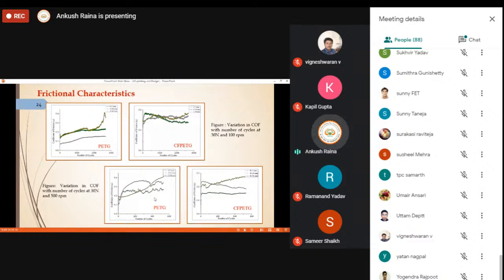So a similar case study has been done at the high speeds. Here you can see again there is an increase, and the coefficient of friction is in the range of 0.2 and 0.3. But here the carbon reinforced PETG has shown less coefficient of friction, and the behavior of these curves is quite good in comparison to this one. The curves over here are staggered, but the curves over here are smooth. And in these two cases, you can see that the coefficient of friction is decreasing with the increase in number of cycles, and that basically should be the requirement of a particular material from the tribological point of view.